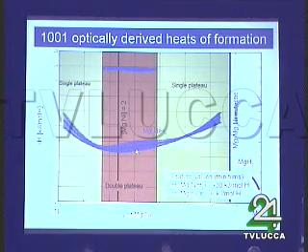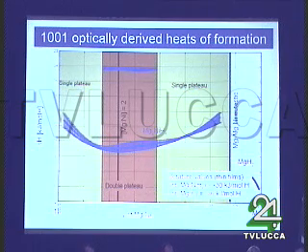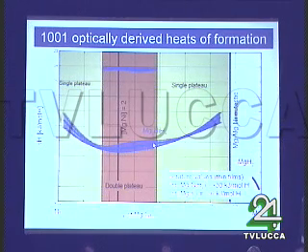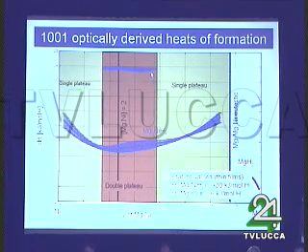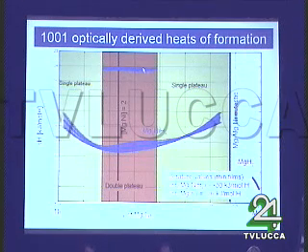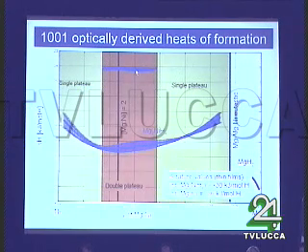What we also find as a function of concentration, you see this here would be magnesium, no, this is 1-to-1 roughly, and this will be magnesium rich, okay? We have three regimes, one where we have two plateaus. No, it's not new. Many people have had two plateaus in magnesium nickel. But in thin films, we have a plateau here which is at minus 24, and we don't really understand why it happens, but it really happens. And this would make magnesium nickel an interesting material.